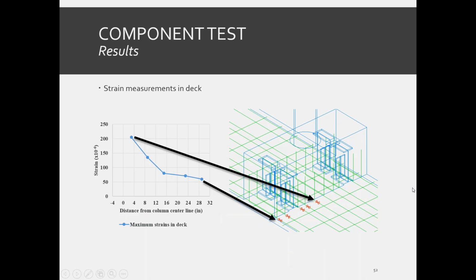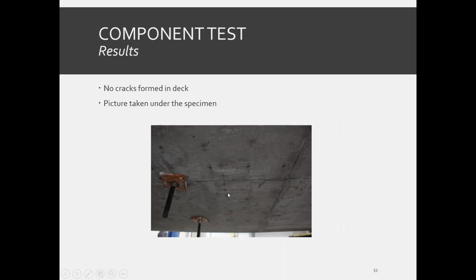And in this figure, the measured strain in deck longitudinal rebars corresponds to the strain gauge locations. The strain gauges are located just outside the diaphragm. Due to the symmetrical condition of the slabs, only half of the rebars were instrumented, and the graph shows that the deck remained elastic during the whole experiment. And also you can see in this picture, taken from the bottom of the deck, that the deck remained intact without any appearance of any visible cracking.